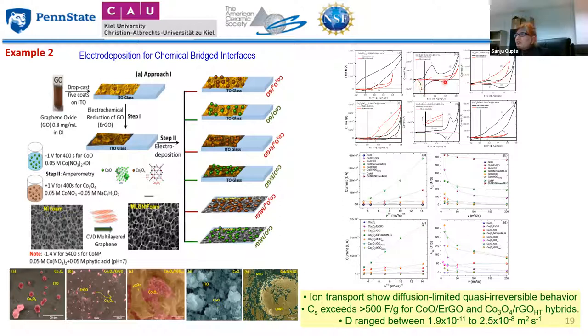And then these redox peaks, as you can see, occur at certain potentials, so that shows that there is a good interaction between these nanoparticles and the graphene. And therefore, it is important to measure this potential with respect to the reference electrode. So it's a three electrode assembly. And then of course, we did the same thing. We also plotted the current versus square root of scan rate, which also allowed us to determine what we call the diffusion coefficients, diffusion of these ions. It allows us to determine whether it's diffusion limited or reversible or irreversible behaviors and things like that. And then the capacity of certain systems exceeded 500 farad per gram. And industrially, 500, 600, 400, these are all good numbers as far as the capacity goes, okay?